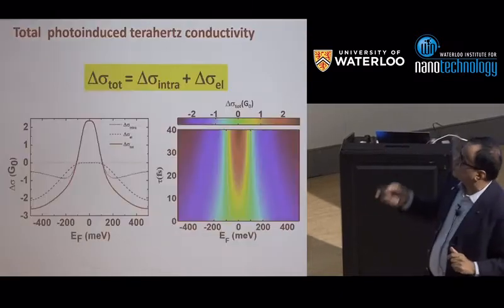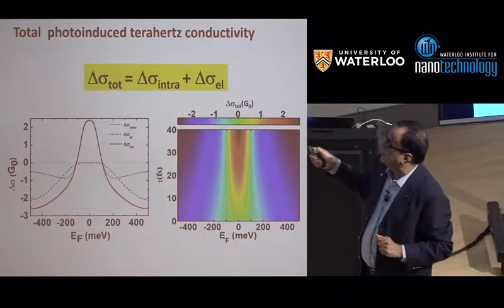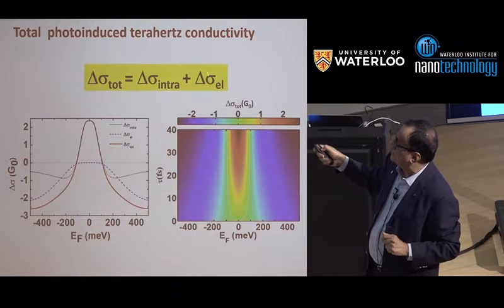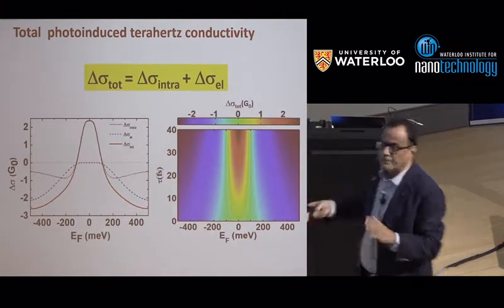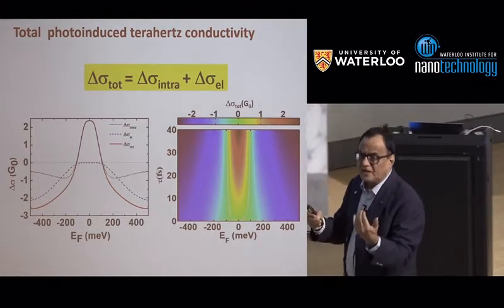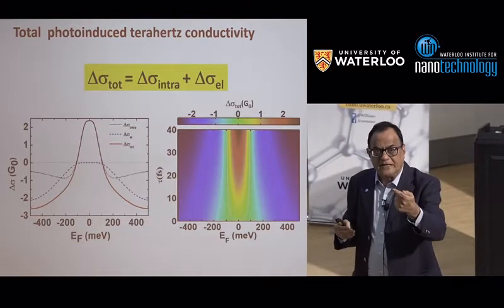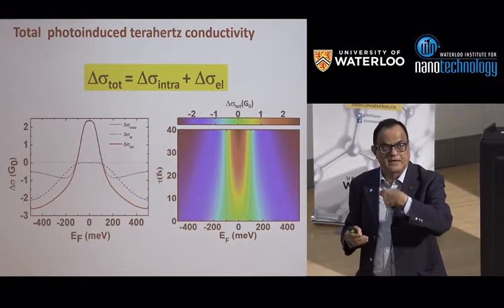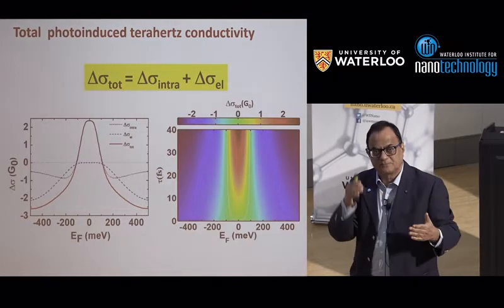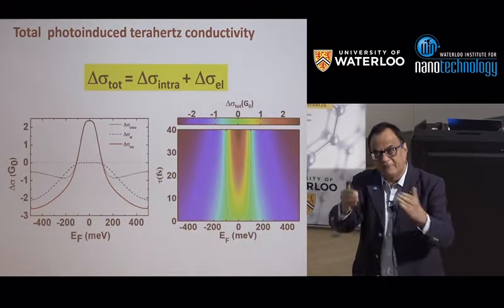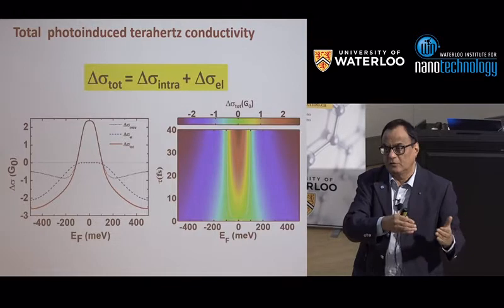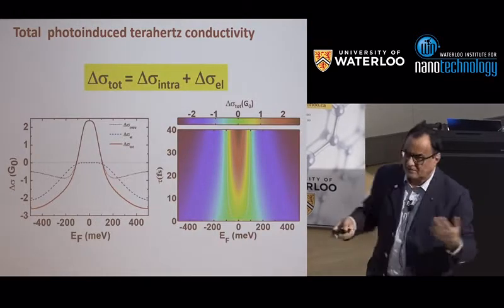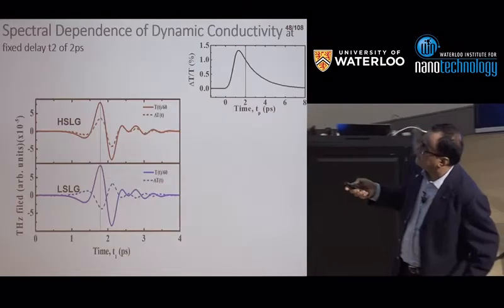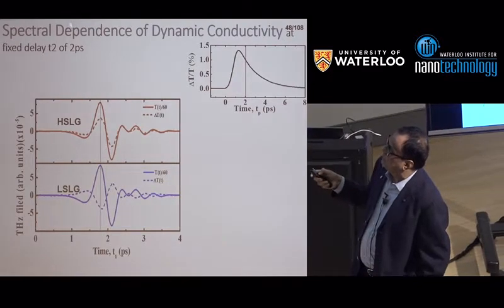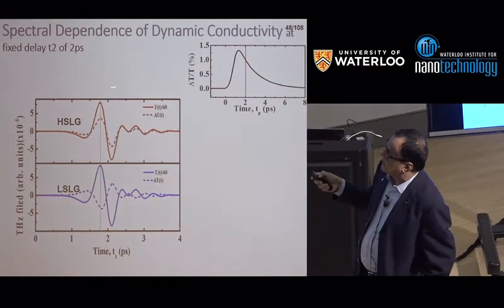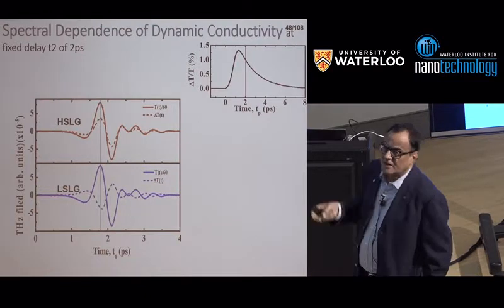So now you put both of them together, intraband and this hot carrier electron mechanism, and we showed you have a master plot now. If you give me a graphene with the known Fermi energy, both the mechanisms put together can explain where you will get negative photoconductivity and where you will get positive photoconductivity. So that was one thing we started with, but then we went on, and this is the part which is quite intriguing. We now want to measure